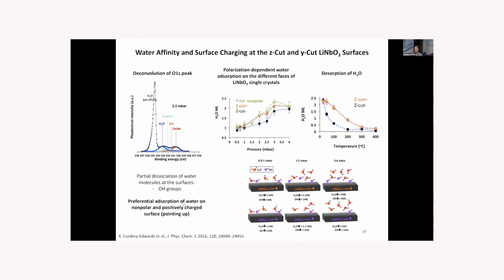They could see that the water preferentially adsorbs on the nonpolar, as here in green, and positively charged surface, the orange curve here. And also the desorption occurred differently for the positively and negatively charged surfaces. For the positively cut surfaces, the desorption took more time and more temperature to occur.